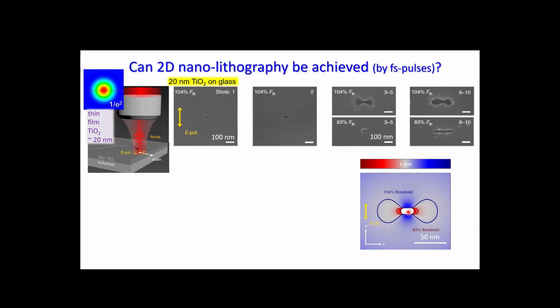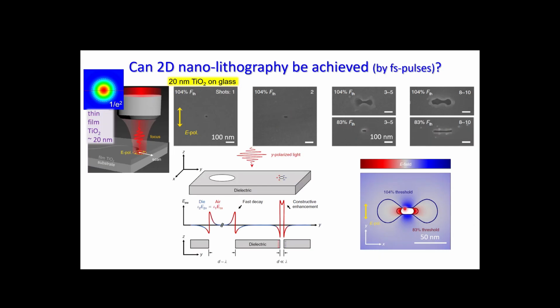So there is ablation in the film, and we see how light is distributed. 80%, 83% of light is really focused on this horizontal line. What is important at the interface, what is defining the light intensity distribution, is that inside the film we have low intensity, and inside the ablated place where there is air it is actually very high. And this comes from the boundary condition requirement that the normal component of the displacement field should be continuous along the interface when it is a dielectric, not a conductor. So the electrical field in air is much higher than the electrical field inside titania.